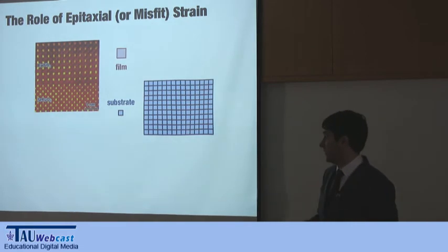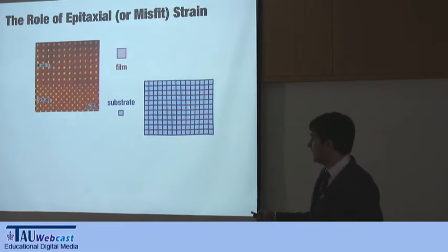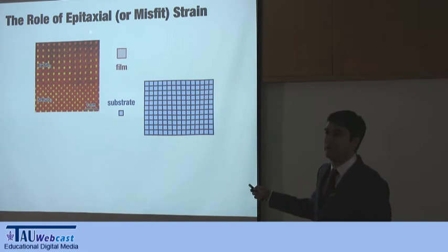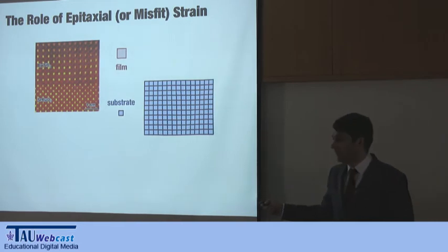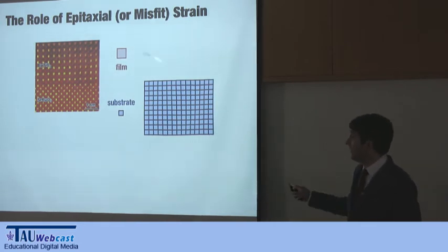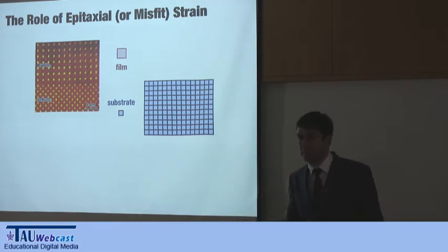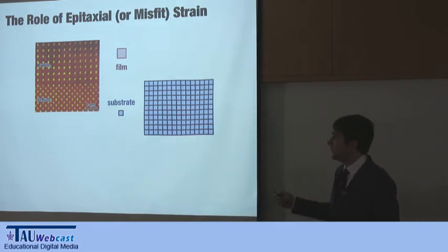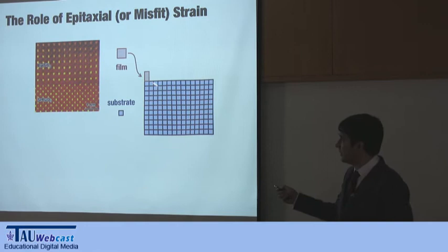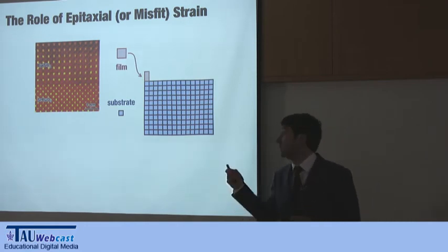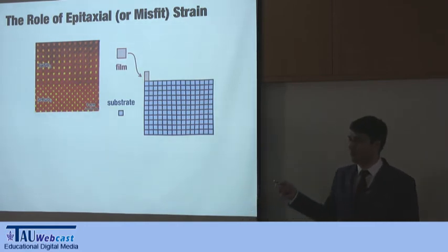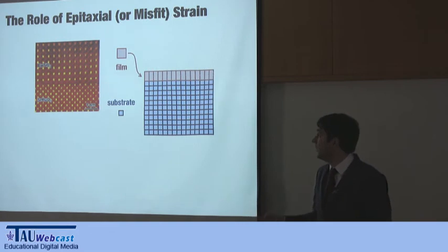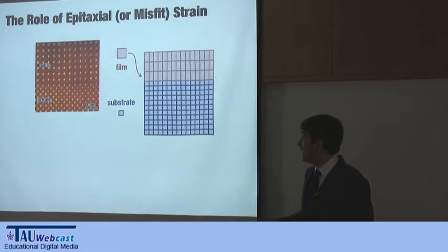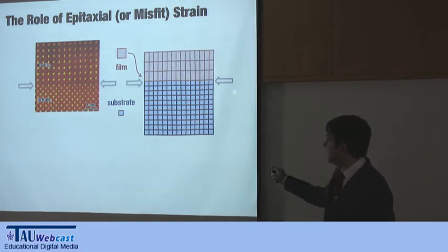So again, to make the point, if you have a substrate and you are going to grow barium titanate on top of it, barium titanate will have some lattice parameter. But because you grow it layer by layer with molecular beam epitaxy or some kind of chemical vapor deposition, when it grows here, the unit cell is going to have to adapt to there. Okay, and you do it layer by layer, and the next layer adapts, and the next layer adapts, and in the end, you end up with some strain here.